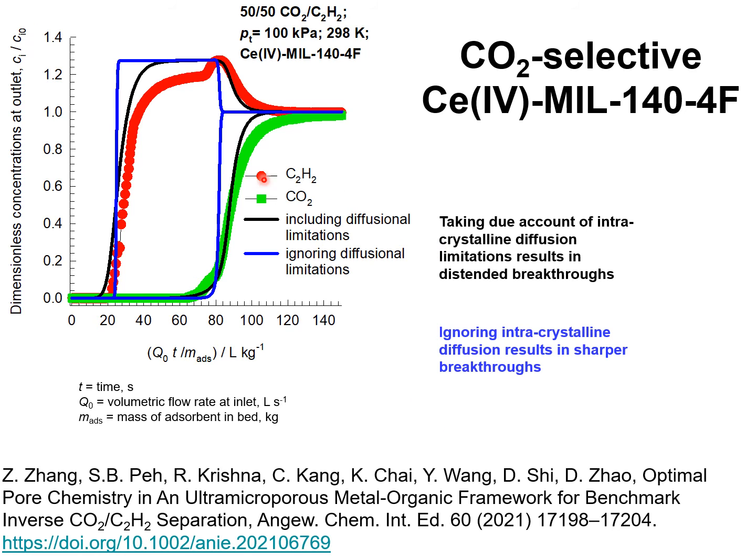The message we draw from this comparison is that for a realistic prediction of productivities of desired products in transient breakthroughs and fixed bed adsorbers, we need to consider intra-crystalline diffusion limitations.